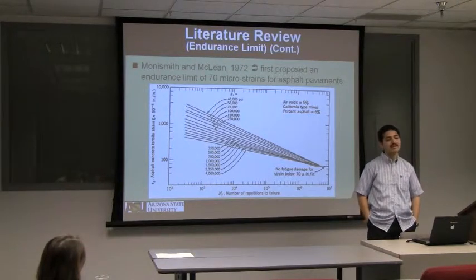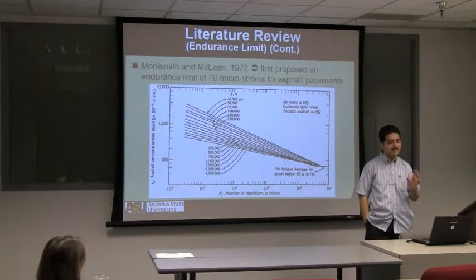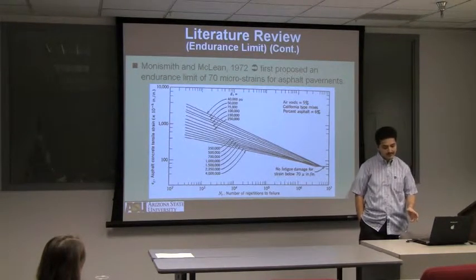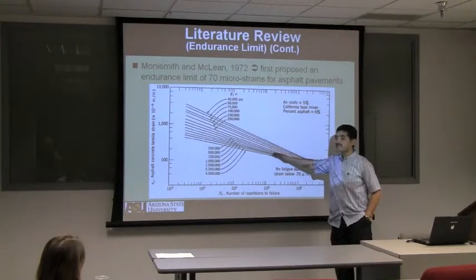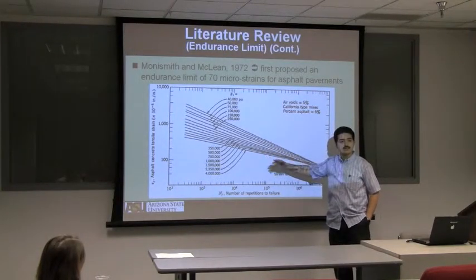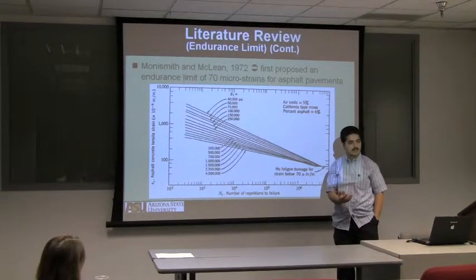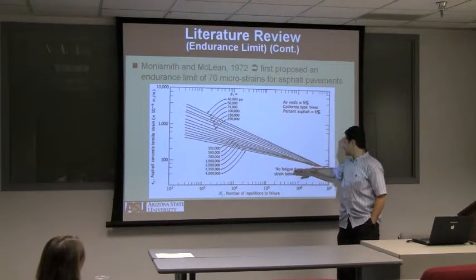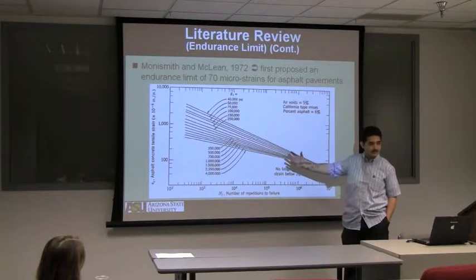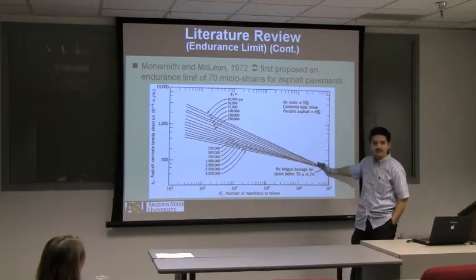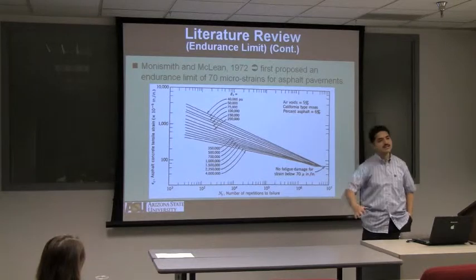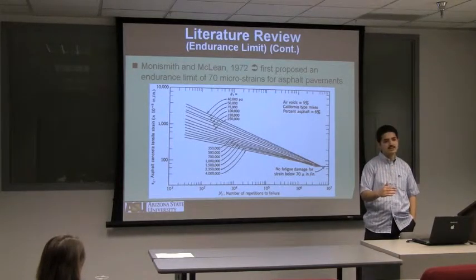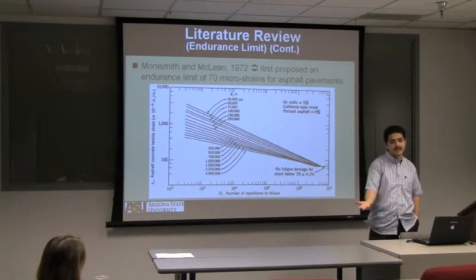So Monismith and McLean in 1972, they proposed that the endurance limit for hot mix asphalt is about 70 microstrains, and they did several stiffnesses. These lines represent different strength of the pavement. Again, pavement strength can vary based on several factors that I'm going to talk about. But what they said is that the endurance limit is constant regardless of the stiffness, and this conclusion I kind of disagree with, because I still believe that endurance limit will change by changing the strength of the material. But at least that's how they started.